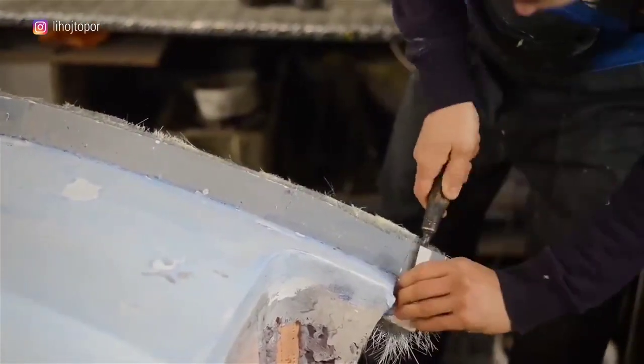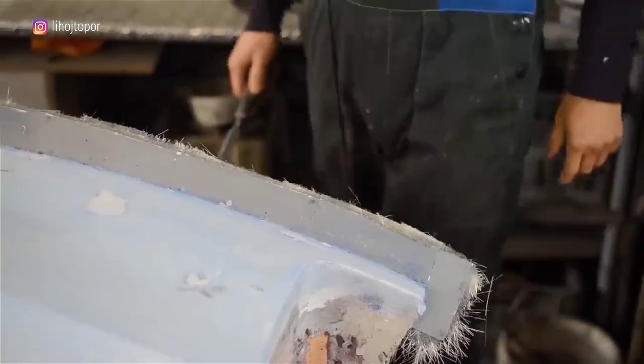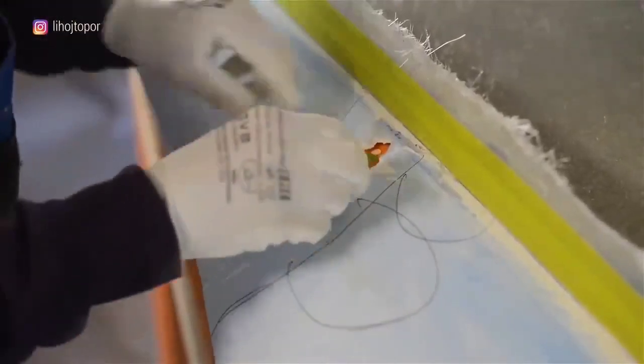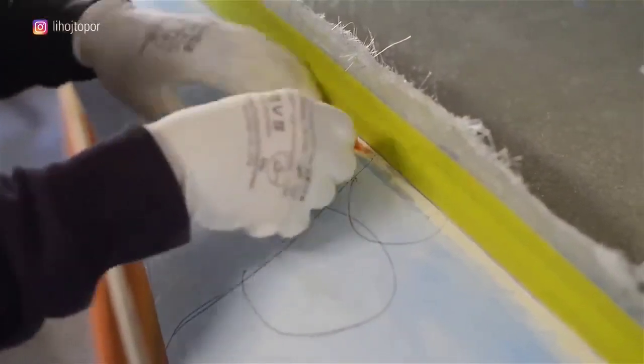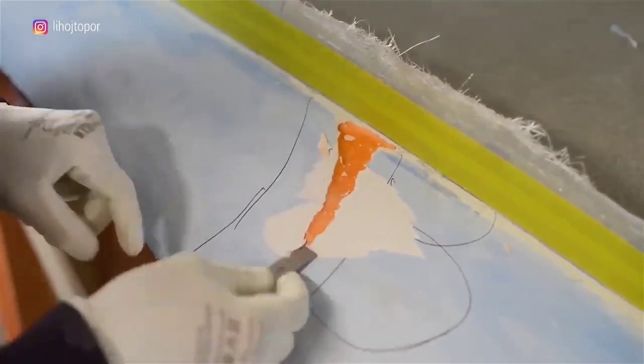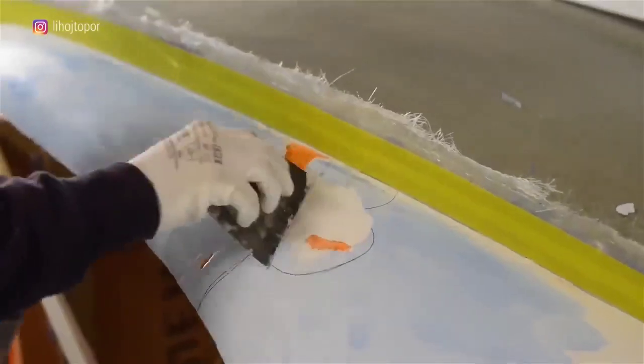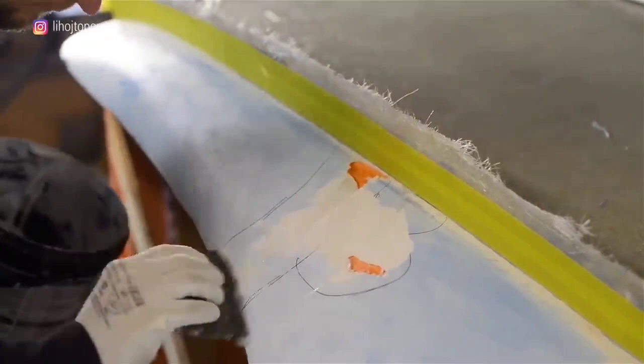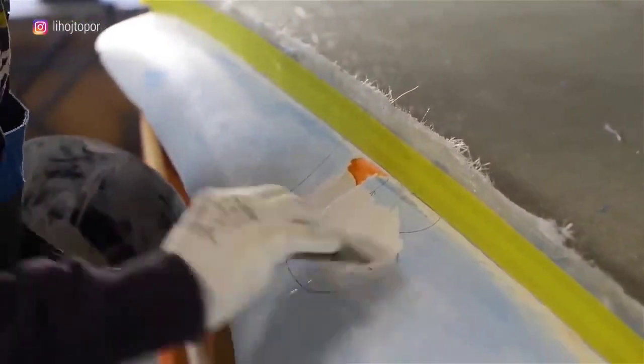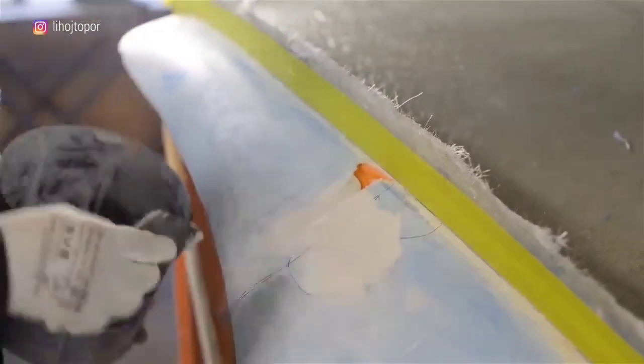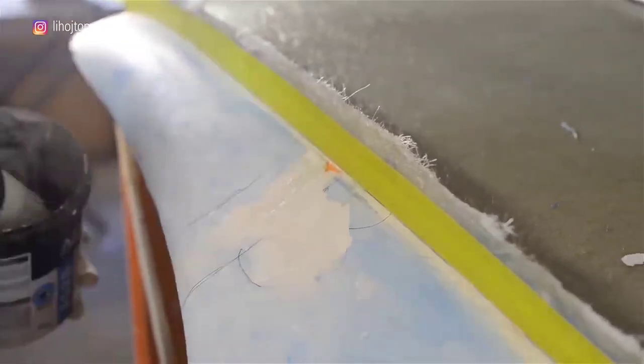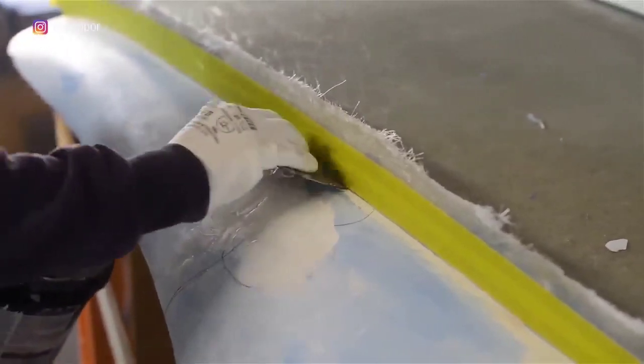And we will get the right design, but once again a surprise was expecting us. In some places the resin has found a way out. We peel off the top layer of gel coat, clean up and putty the spots where the resin has eaten away the workpiece. The rest was done in the same way. A few days we covered it with the glass fiber mat layer by layer, and now we have a finished matrix which should be detached, and then we'll evaluate the result.